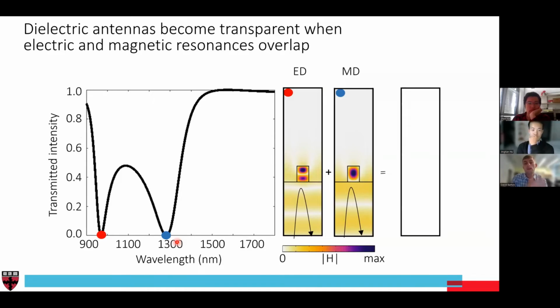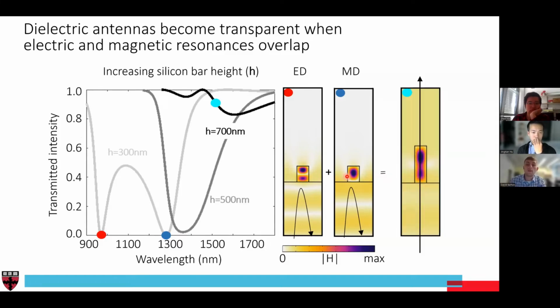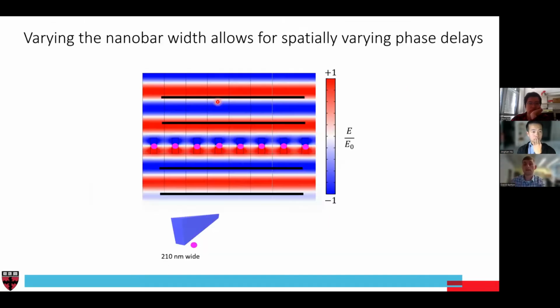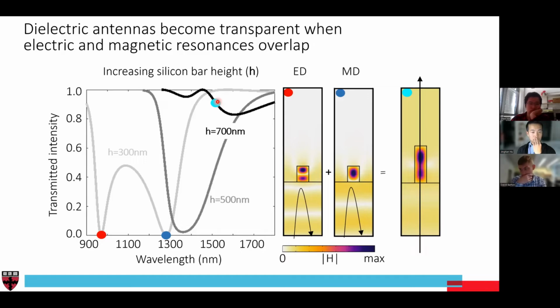But if you engineer the material differently, and for example make your structure very tall, in this image on the left, the position of these resonances shifts and they align on top of each other. What we end up finding is that the transmission goes very, very high. You can get nearly 100% transmission when these resonances overlap. If you've ever worked in the field, this is called a Huygens-type metasurface, and it's well known that you can get these resonances to overlap, and then your transmission will go up. This is one common way of designing these metasurface elements.